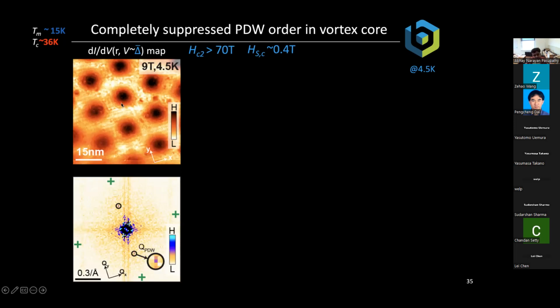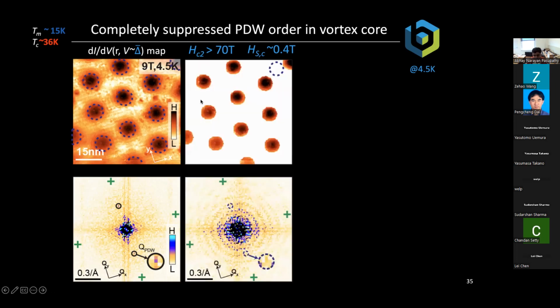And so we can ask ourselves, does this phenomenon, these stripes that we see, persist inside the vortex and outside the vortex? Outside the vortex, even by eye, I hope all of you can see that these stripes still survive. So you can see these stripes beautifully running outside the vortex. Inside the vortex, looks like there's nothing. We can confirm this with a Fourier analysis. So what we do is we make a little mask that goes into the vortices. We just keep those regions of the sample and cut out everything else.